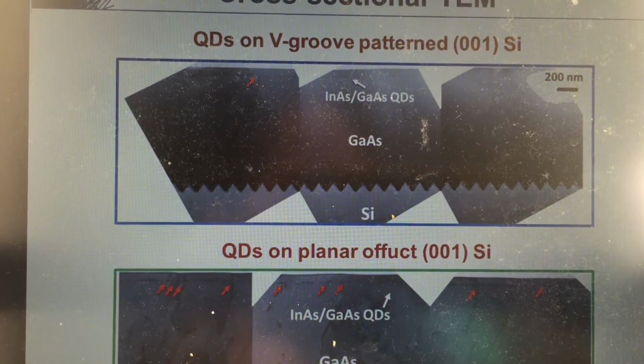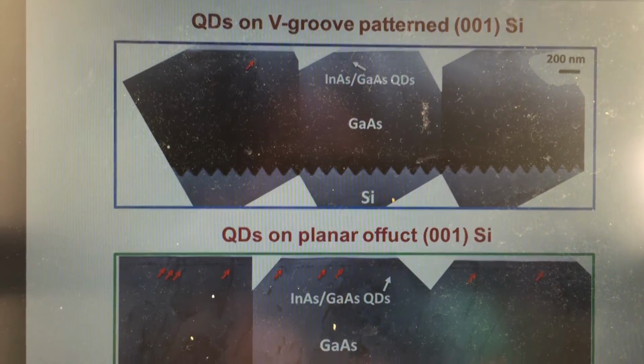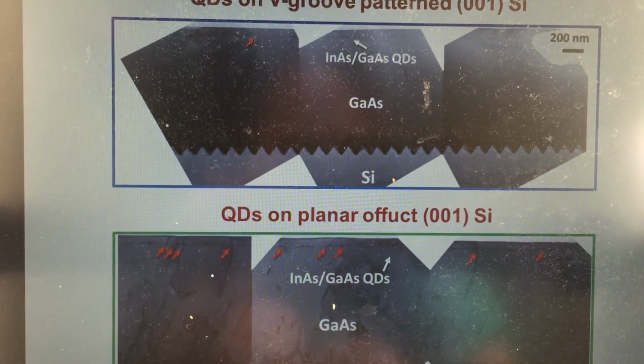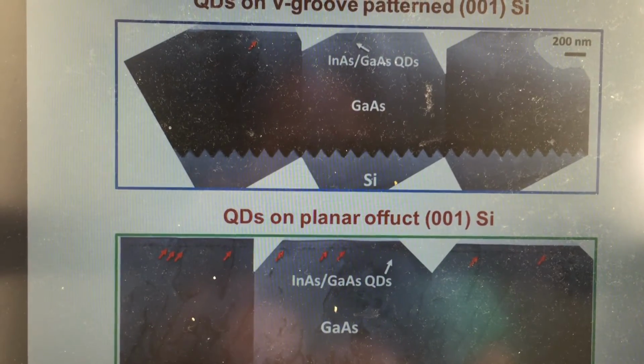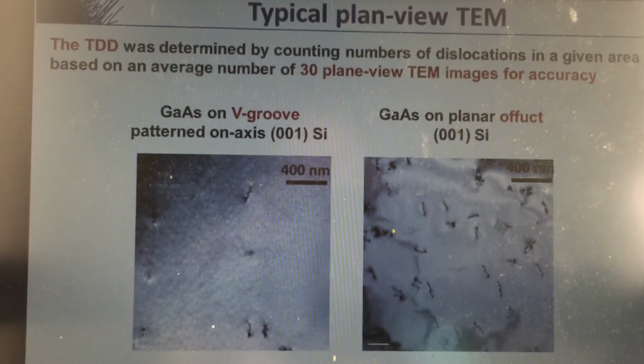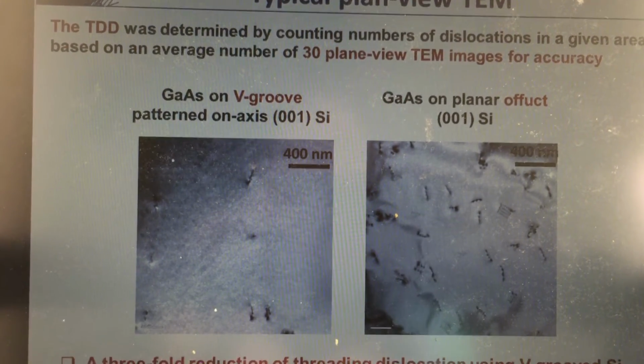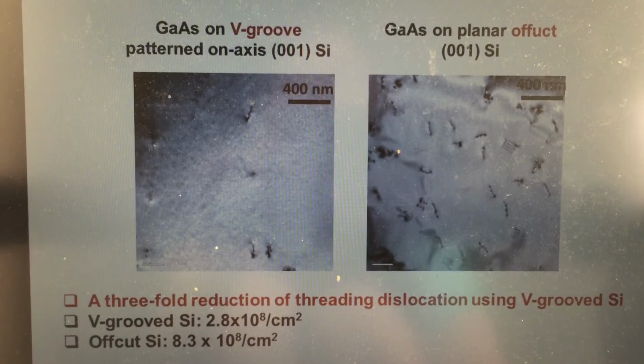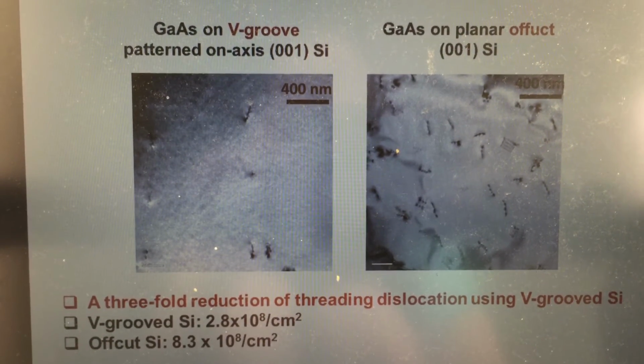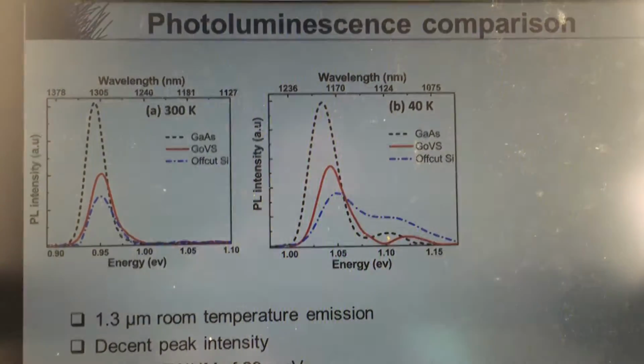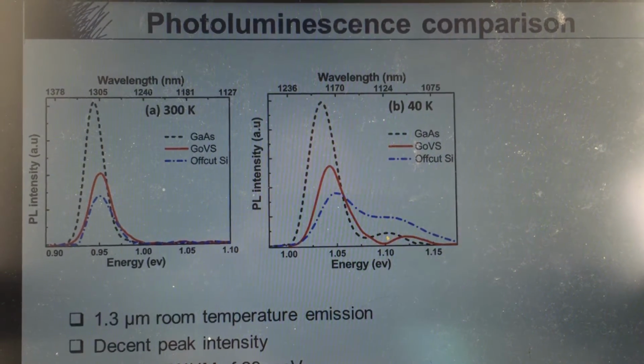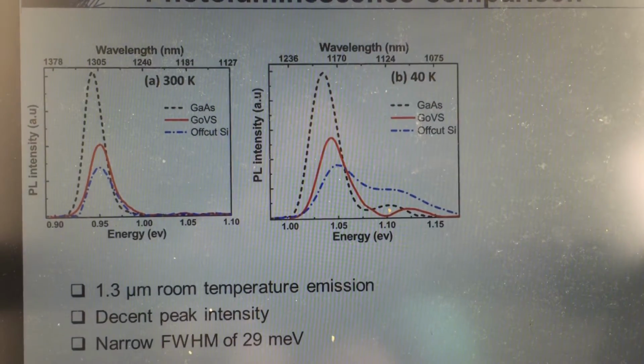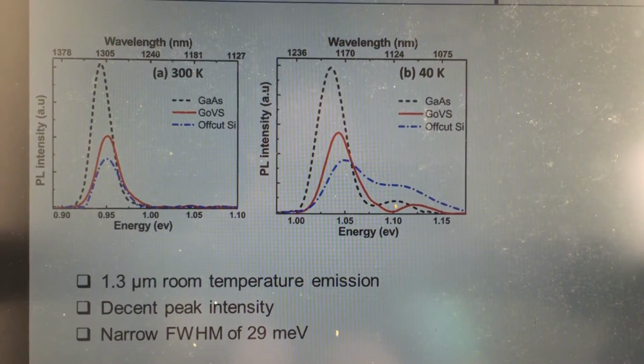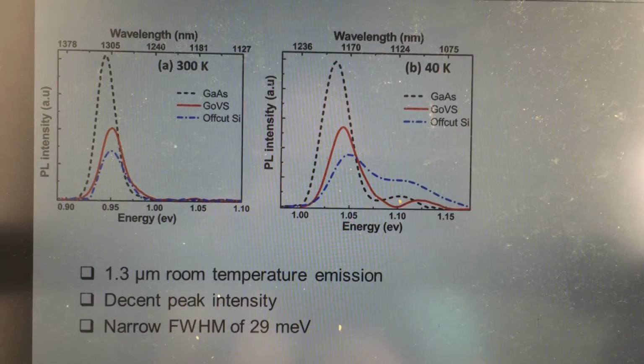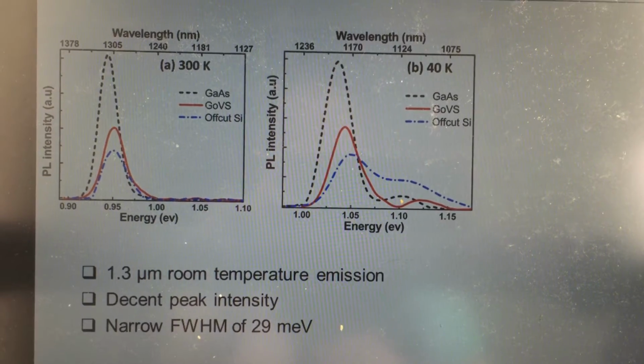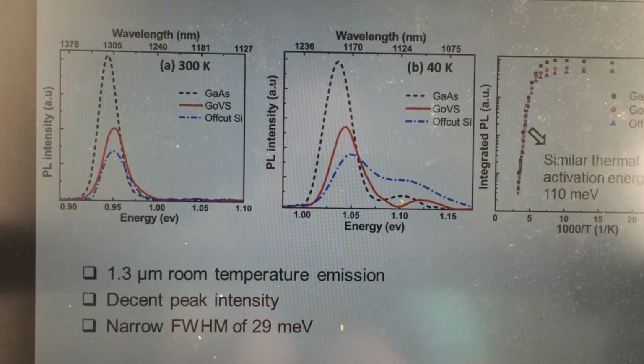Actually, on the larger scale, our GoVS substrate is not totally defect-free. However, there are much more defects in the active region on the off-cut silicon template. To be more quantitative, we calculated the threading dislocations according to plane-view TEM images, and we find a threefold reduction of threading dislocations using the V-groove structure. Here is a photoluminescence comparison at both room temperature and low temperature. And we find the GoVS substrate has obtained a 1.3 micron room temperature emission from quantum dots with a narrow full width at half maximum of only 29 meV.